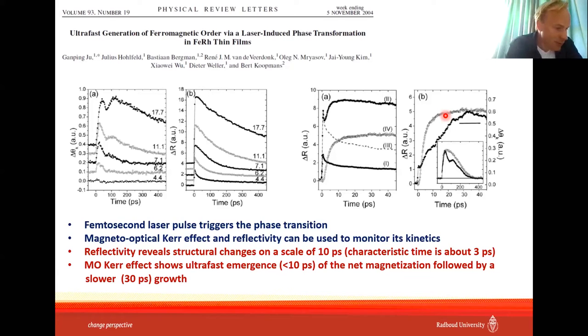So there is also a comment from Ivan that it's not a coherent process, it's a diffusion. So it's a very relevant comment. It is what you can see here. If you don't see relaxation, it's more like thermodynamic. You can explain it in terms of quasi-equilibrium thermodynamics. So basically, it's a heat transfer from electrons to lattice, and as an effect of the lattice heating, the lattice expands. In principle, if you do this heat transfer much faster than the period of a specific mode in the lattice, you can trigger coherent oscillations of this mode.